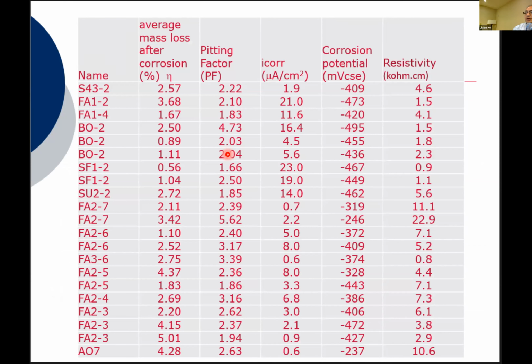I'm going to take a moment to show you that in some cases you can have relatively high resistivities and relatively high corrosion rates, whereas in other cases with the same concrete composition, you can have low resistivities with even modest corrosion rates in this case. But the reason for that is that likely this particular specimen had a larger crack, so the measured resistivity is smaller with the solution that is